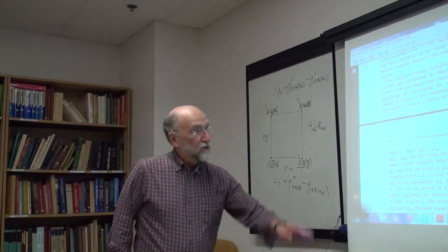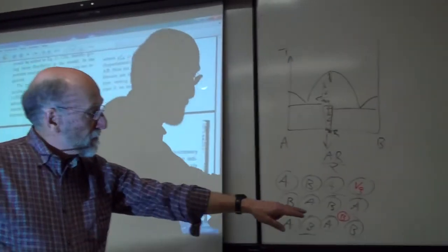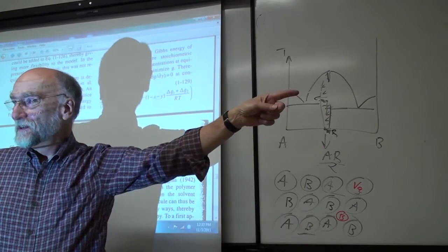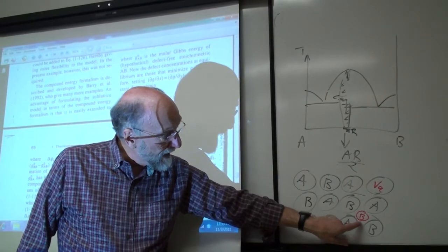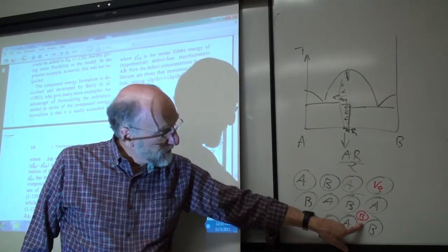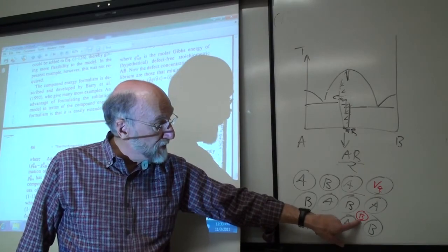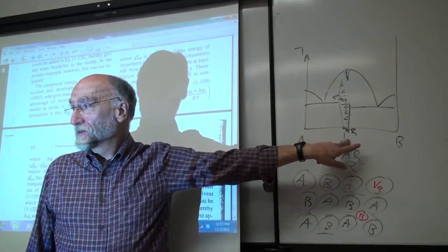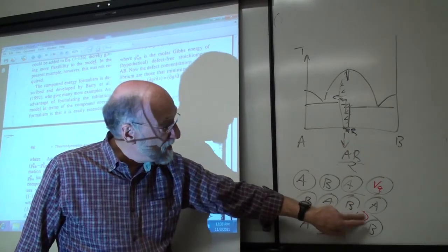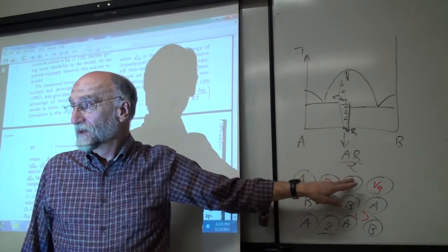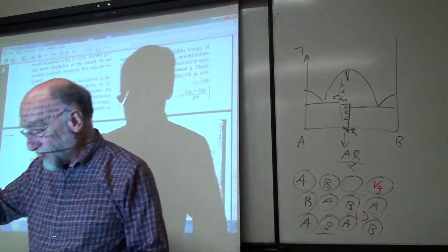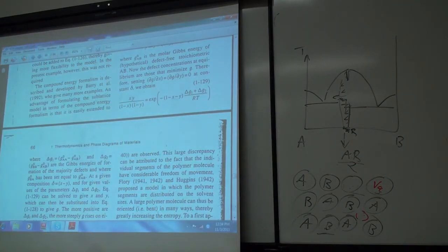Let me give you an example. Supposing you use this model, and then we go into the ternary system and add C. Now let's say C is a bigger atom than B. In that case, if C is a big atom, it isn't going to go in interstitially. So your first guess, if you had no data, would be that C was not soluble in this compound. On the other hand, if B was going in substitutionally with A, then it's easier to substitute here. In that case, C could replace B. In this case, C can't. So how the non-stoichiometry goes is a little more complicated, but an interstitial model is only good if you have smaller atoms.